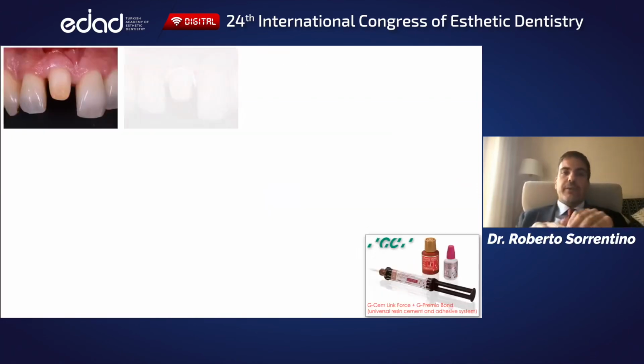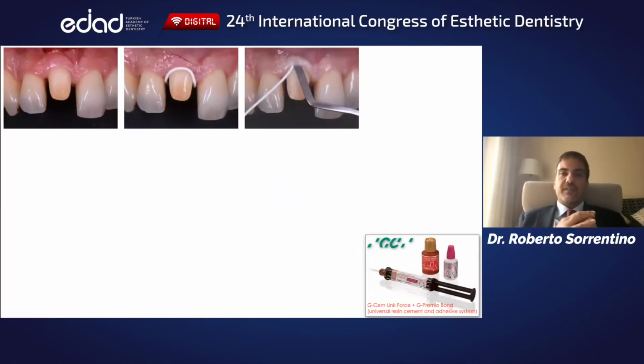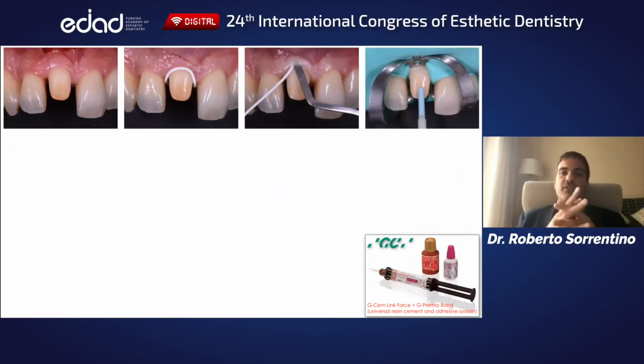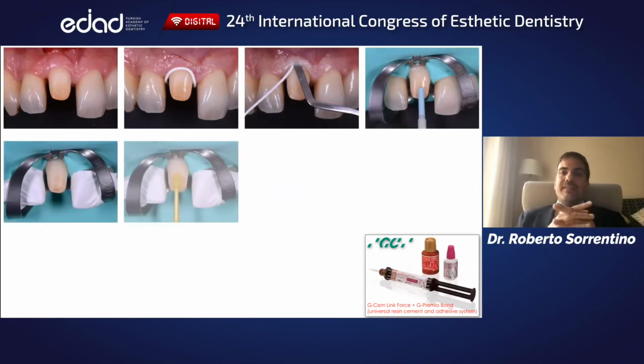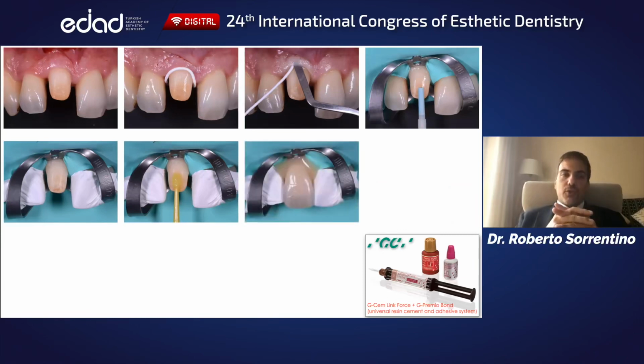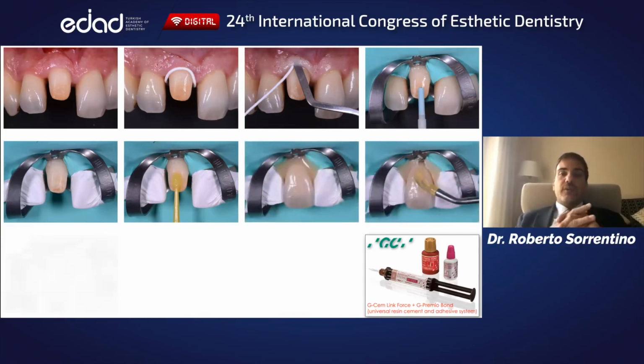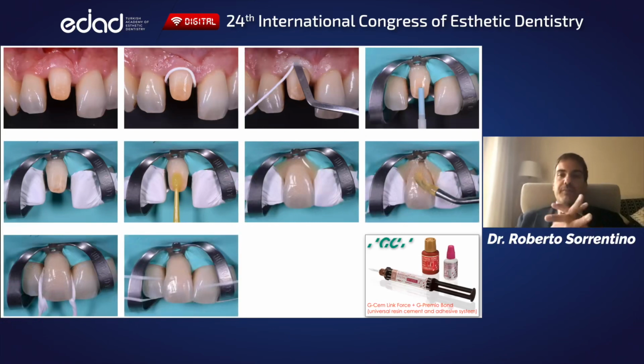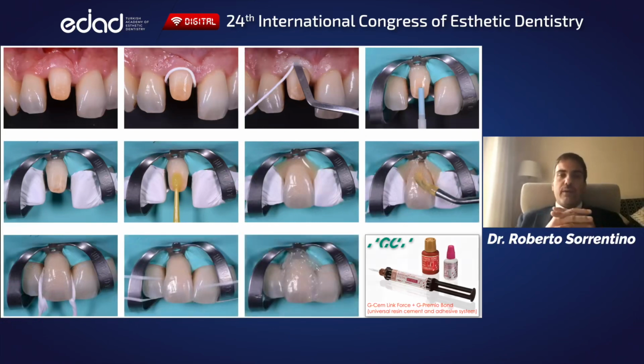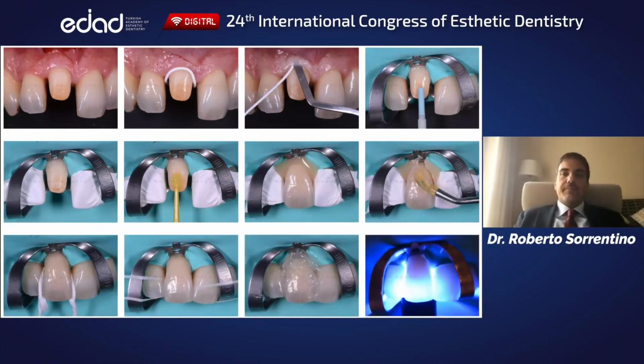Since I had primary retention, I chose a simplified adhesive protocol using again G-CEM LinkForce, but this time with a self-etch approach. Although complete isolation is not mandatory when you go for simplified cementation of full coverage crowns, the use of the rubber dam makes cementation faster and easier.